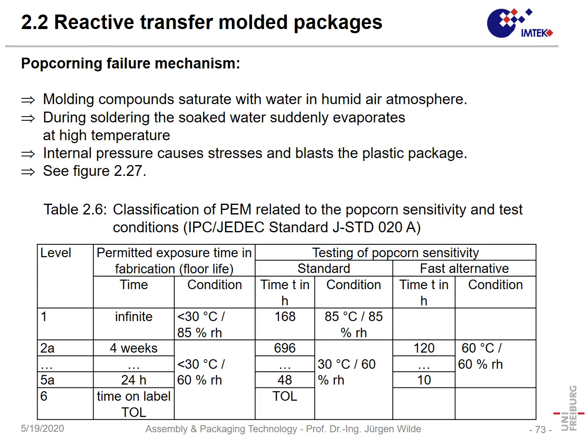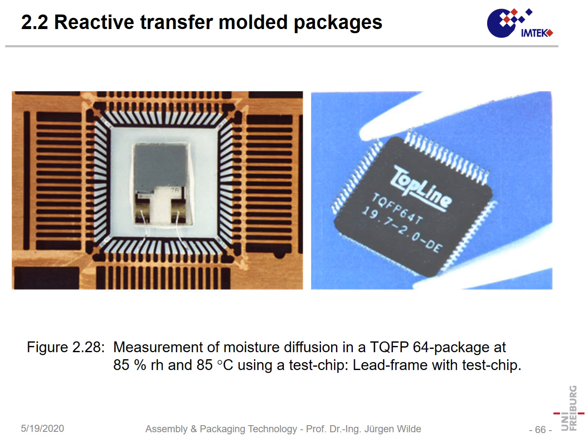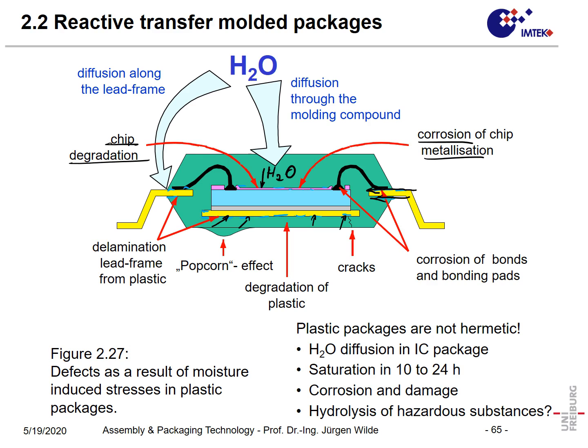On the other hand, when we look at the packages, I said that package is saturated in some way with humidity, and humidity will be found especially in interfaces here. The interfaces are weakened, and also when we go into a soldering at 250 degrees centigrade, this water will evaporate, and the pressure it will build up will be very high. So maybe if every 20 degrees centigrade the pressure increases by a certain factor, then we can see there will be a very high internal pressure on the packages. And that internal pressure will lead to bulging, or it will lead to cracks on the package.